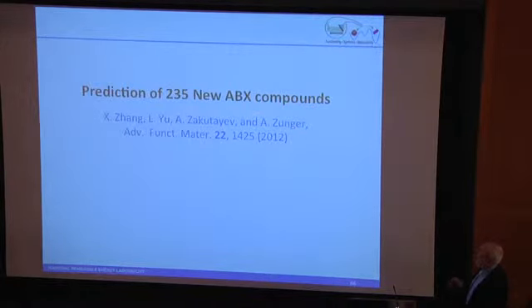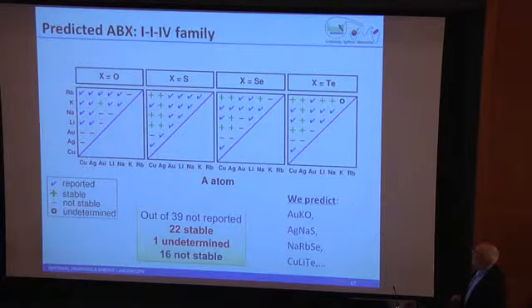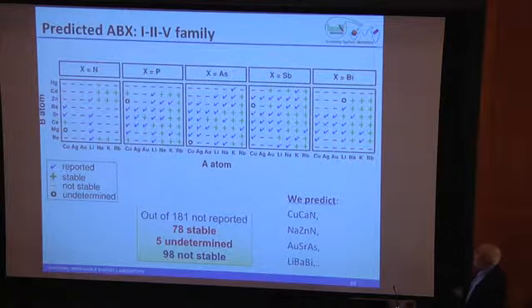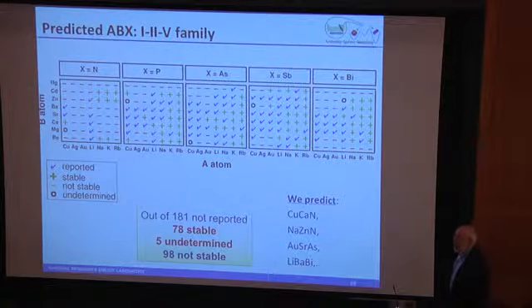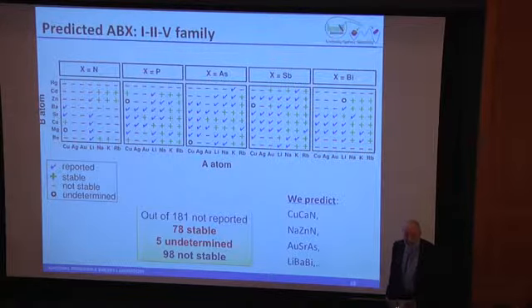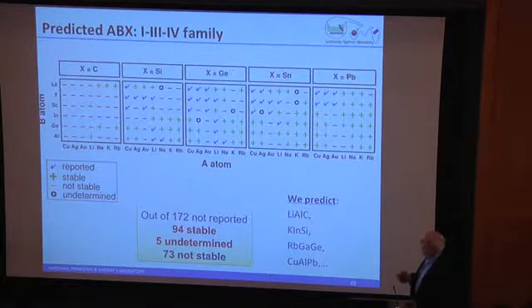Also, we went back and looked at the ABX materials, and you can see that of those, there's also a large number that are predicted to be stable but have never been made. There's a large number of the 1-2-5 family, in fact, a much larger number that should be makeable that haven't been made. And also for the 1-3-4 family.